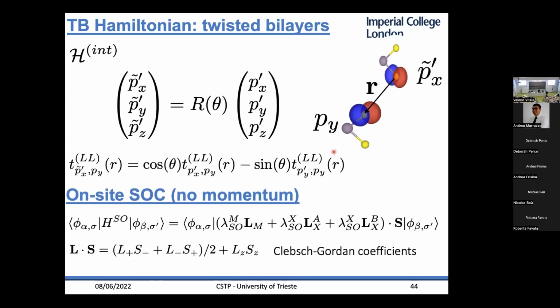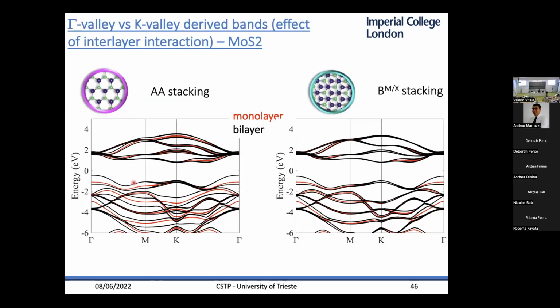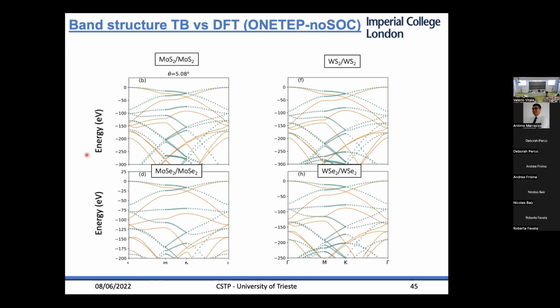Right, so the last two ingredients for the tight binding model were the rotation of the orbitals, of course, of the top layer compared to the bottom layer. We had to rotate the basis, and the inclusion of spin orbit coupling, which in our case is a simple on-site term. It doesn't carry any momentum. So if you put everything together, then you get a tight binding code that generates this structure compared to the DFT.